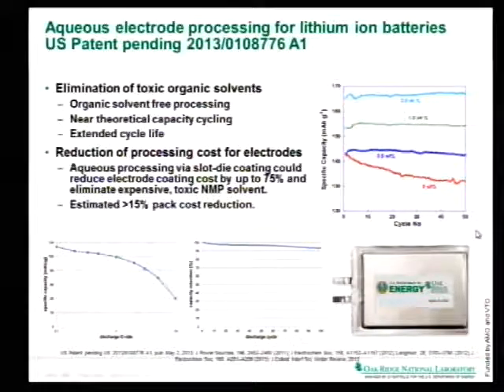And as you can see here, this data shows essentially where we started out. You don't do anything to your system. You end up with a very low performing battery, very low energy density, and a quick fading mechanism. And as we work our way up, we end up with a very good battery with a very good rate capability. This shows essentially the available capacity as a function of how fast you charge and discharge that system.